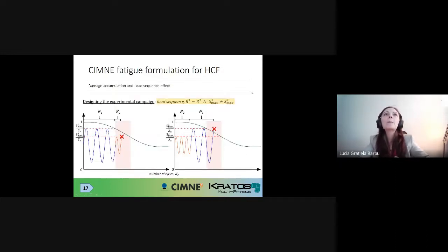Now an important thing for us, and this I didn't mention in the state of the art, just let me say that when you are using the Miner rule, the linear damage accumulation rule, although it is very widely used because it's very easy to use and it's a useful tool for the industry, the Miner rule is not always correct. It has been invalidated for several different types of materials. Why? Because the Miner rule assumes that each cycle of loading has exactly the same degradation level, even if it's the first cycle of loading, even if it's the 100,000th cycle of loading. And this is not correct.